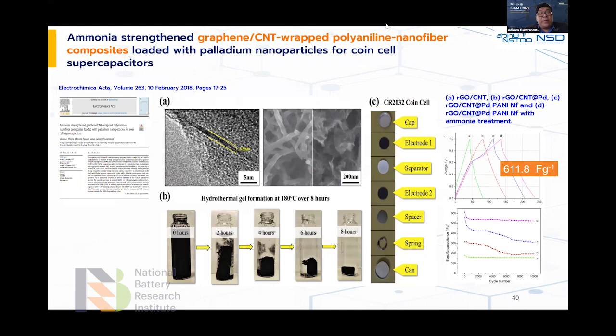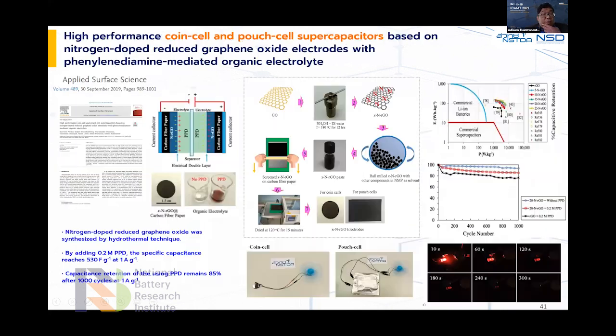And another composite that we recently worked on is the graphene and carbon nanotube wrapped polyaniline nanofiber composite. We are about close to finishing. We can reach about 600 farad per gram. And we also play around with the organic electrolyte system using phenylenediamine-mediated organic electrolyte to increase the performance of the nitrogen-doped reduced graphene oxide electrode in the supercapacitor, and we can reach about 530 farad per gram.